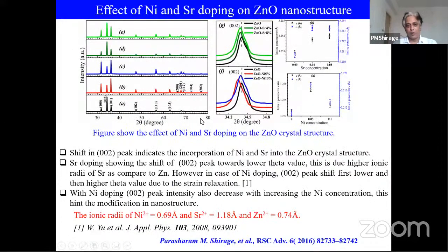Now here comes the doping effect, the fourth parameter. When we replace zinc with some strontium or nickel, for example, zinc has an ionic radius of 0.74 angstrom, and strontium has ionic radius 1.18. Automatically, when we replace zinc with strontium, because of the higher ionic radius, the lattice parameter will increase.